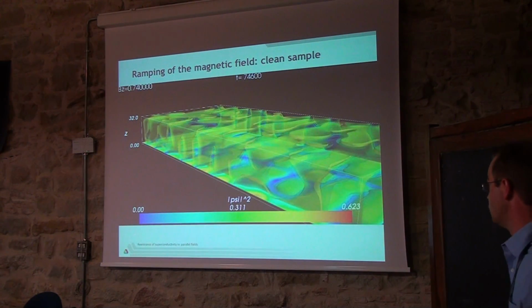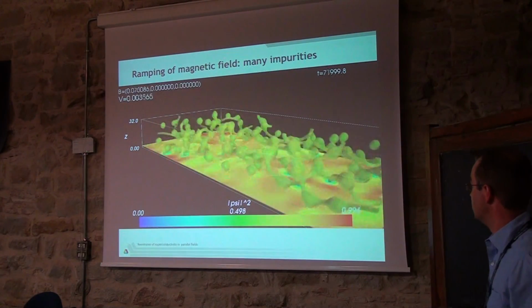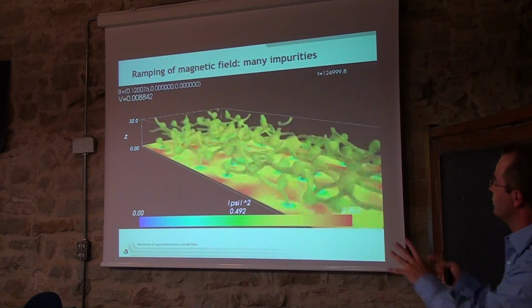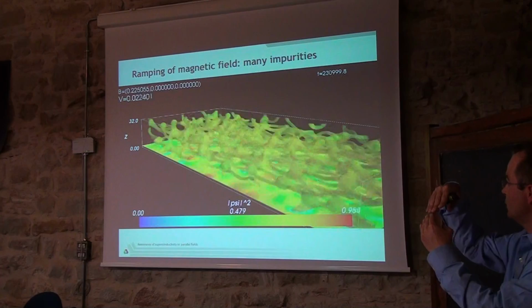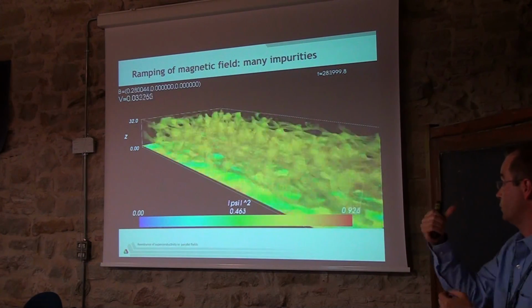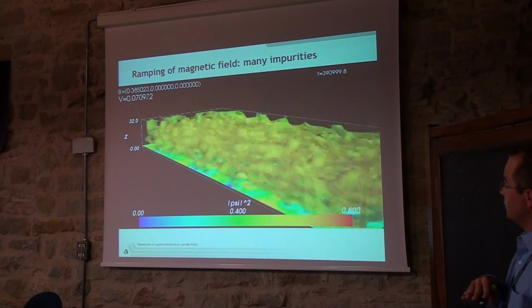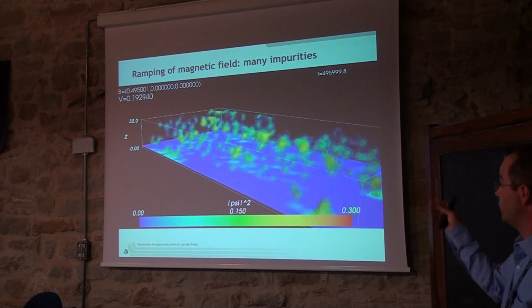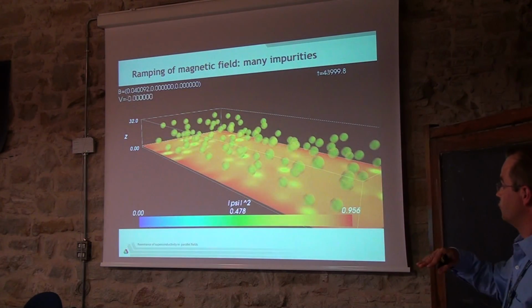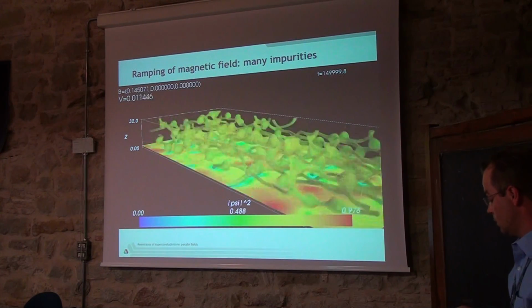So then we tried to add more inclusions here. But if you add too many, then basically all these inclusions bend your vortex lattice in such a way that you always have a Lorentz force and then you always have dissipation. So basically at HC1 you get dissipation, and basically you will never get rid of it. There's no re-entrance and you will always be in a resistive state.